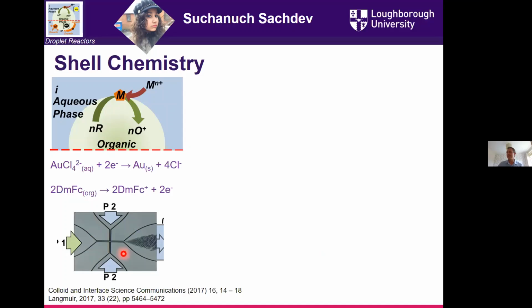And just so that we're clear in the way that we set this up, P2 here is the continuous phase, it's water, and we're making hexane droplets, which is P1. And so the hexane comes out through this channel and makes these droplets. You can see all the individual emulsion droplets. At this point, this liquid here is aqueous, but it doesn't contain any metal ions.